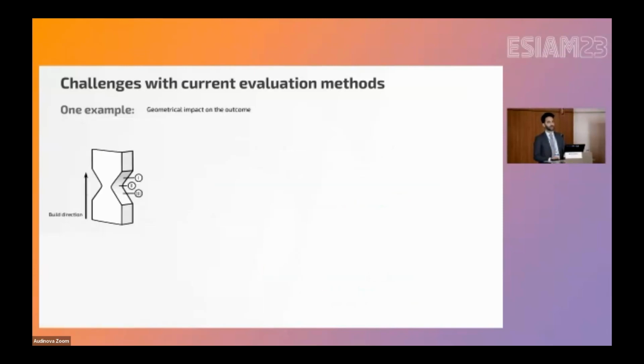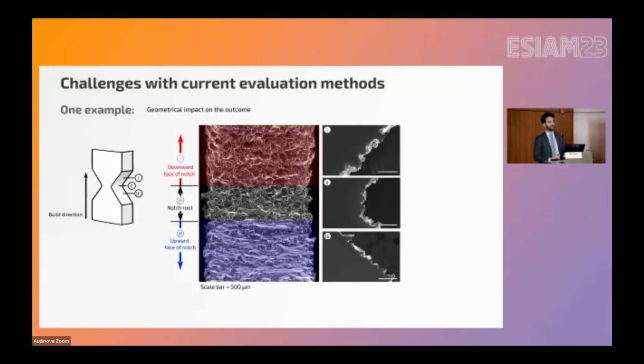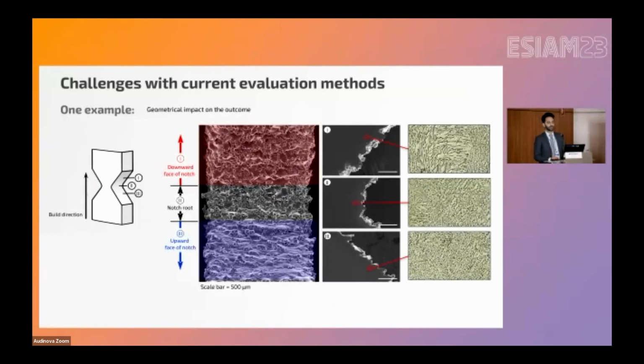Another simple case. We wanted a simple way of checking the geometry effect, a V-notch. It was printed, very classic, you all know. Overhanging areas will give higher roughness. But let's look at the microstructure. This time, within the same component, we see a significant gradient of microstructure, something we usually neglect.